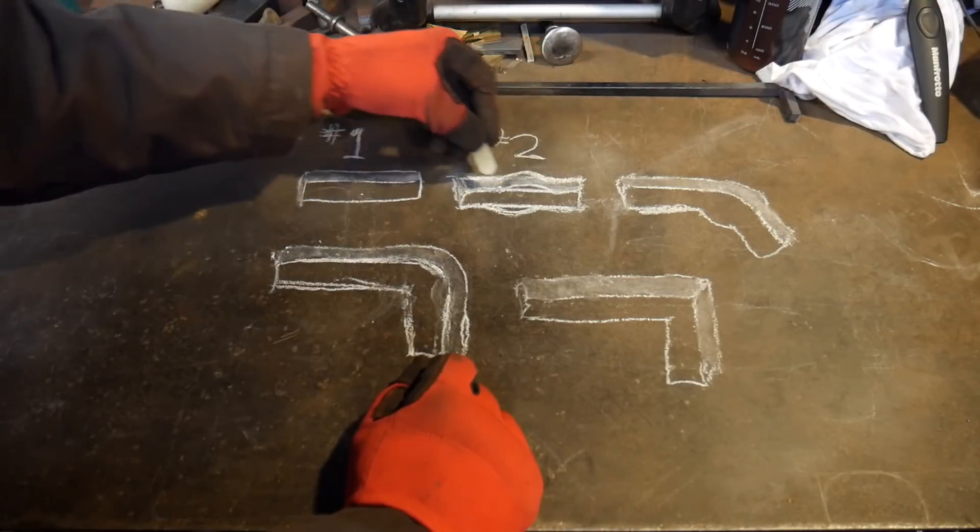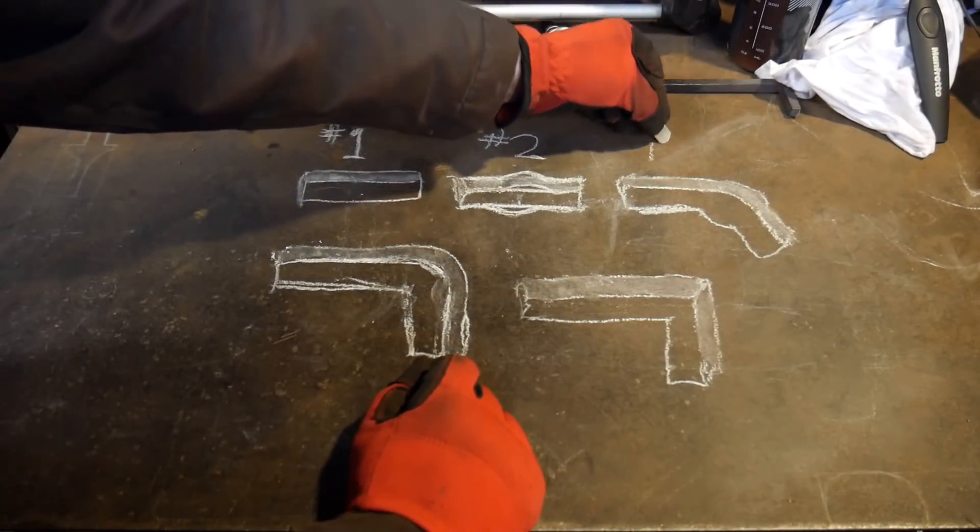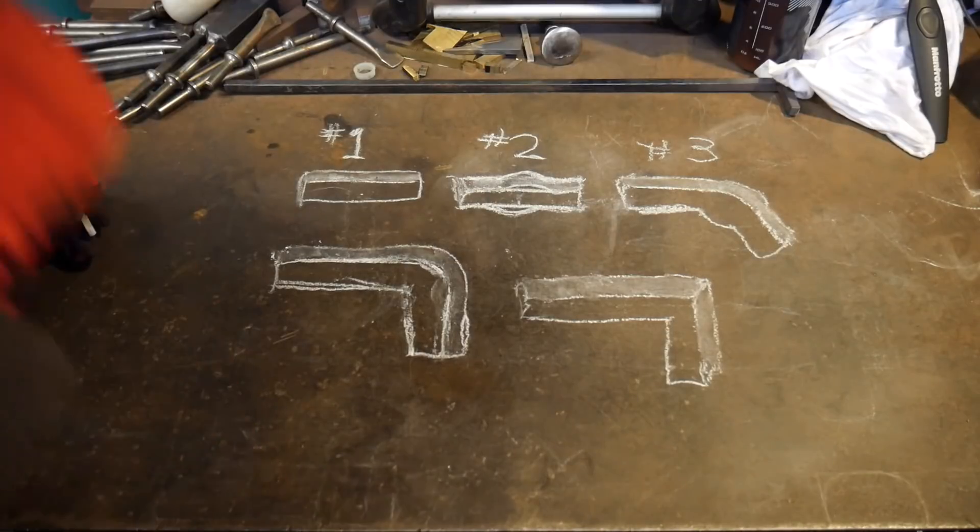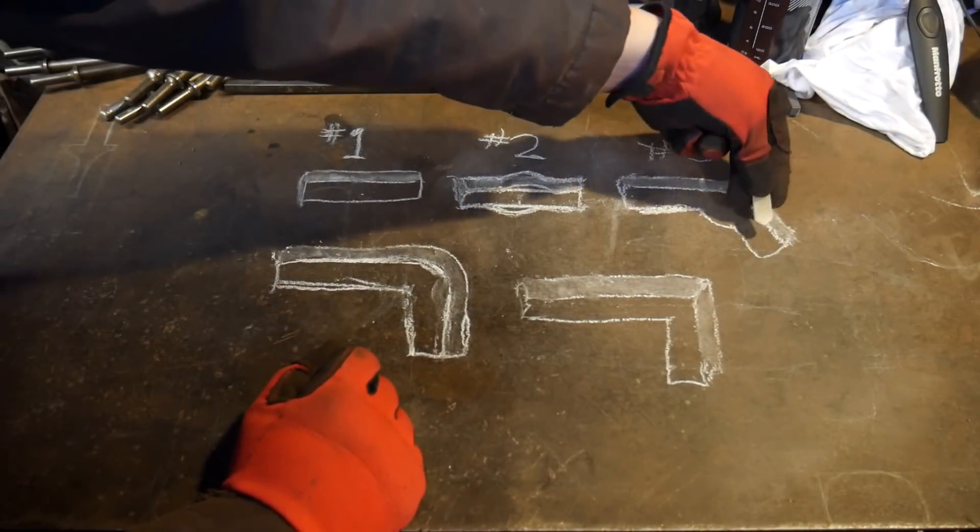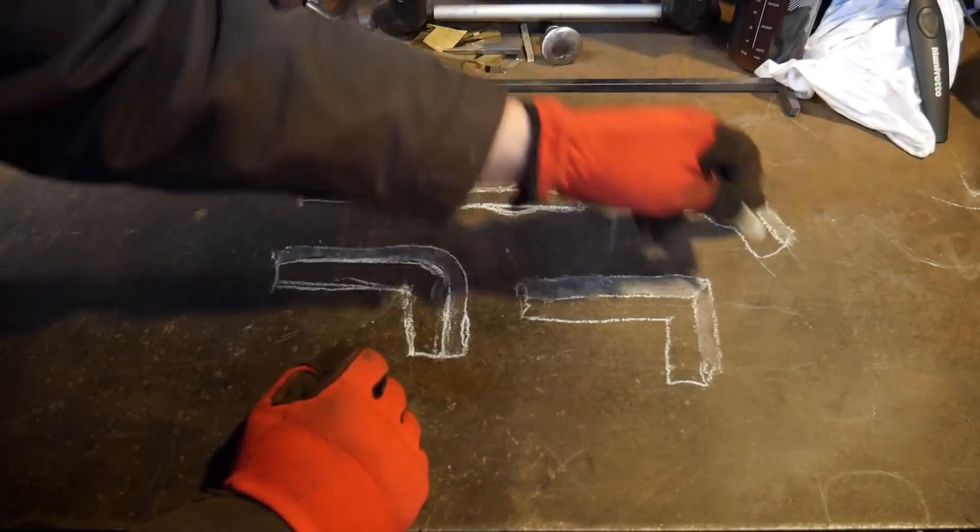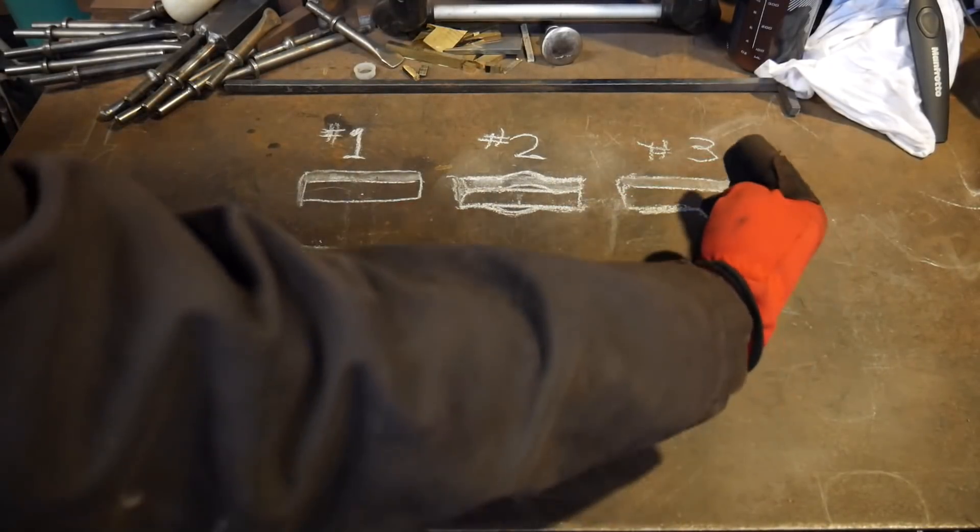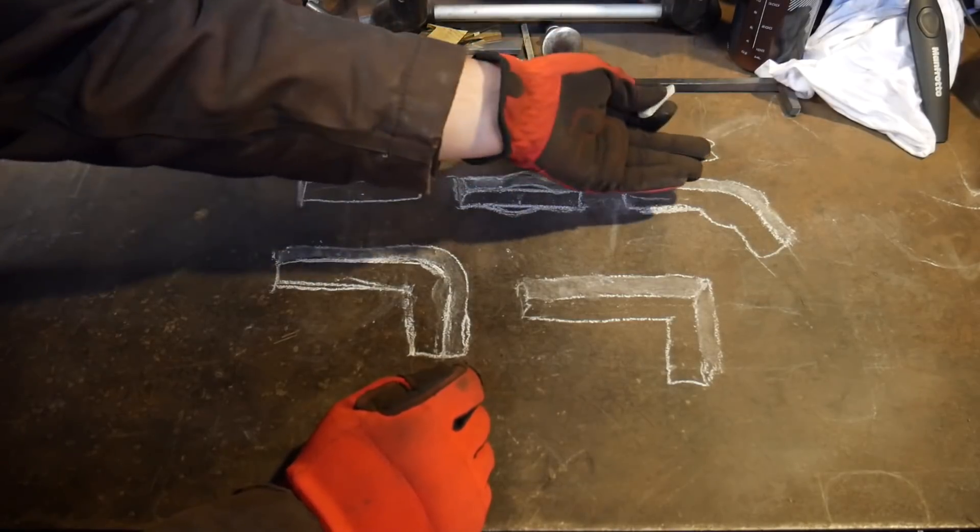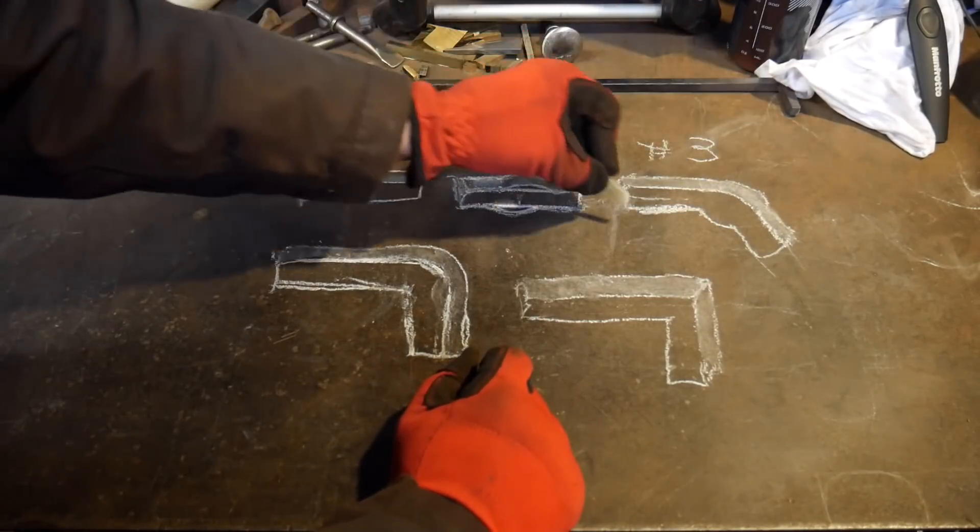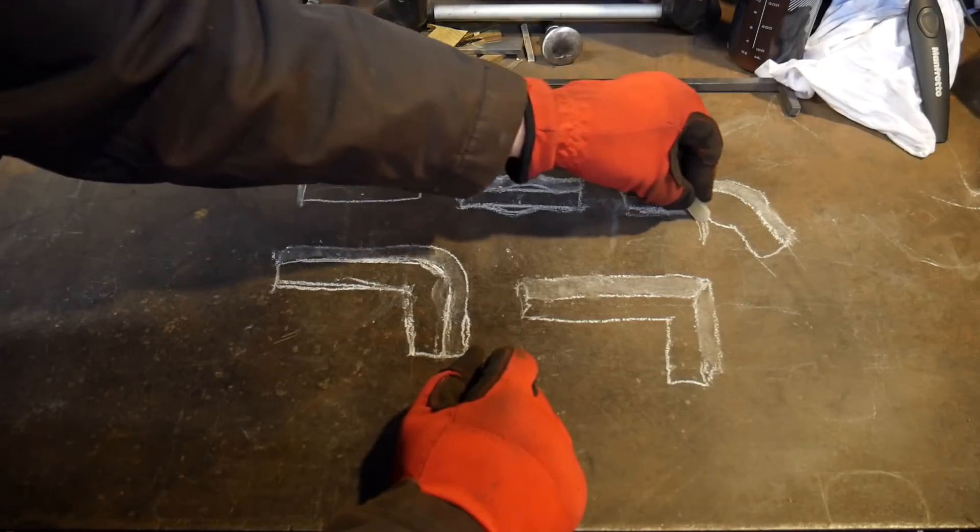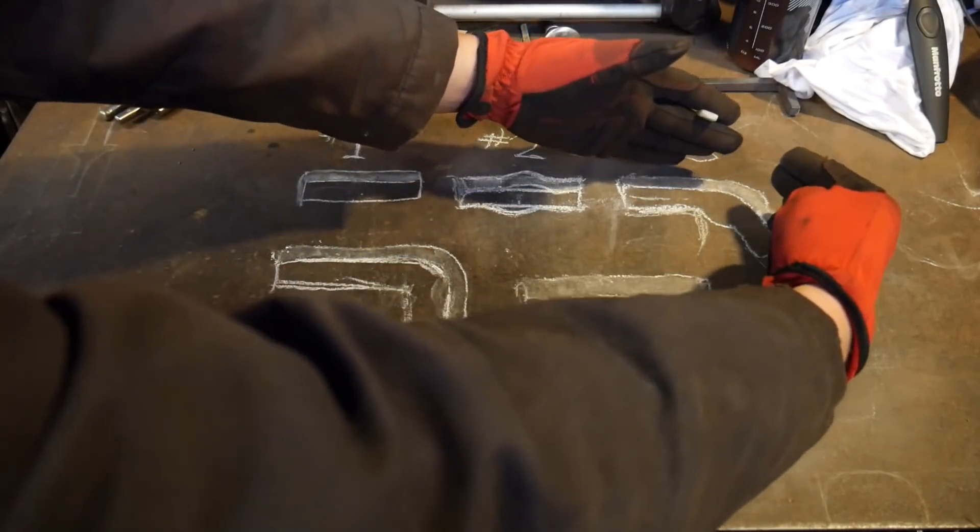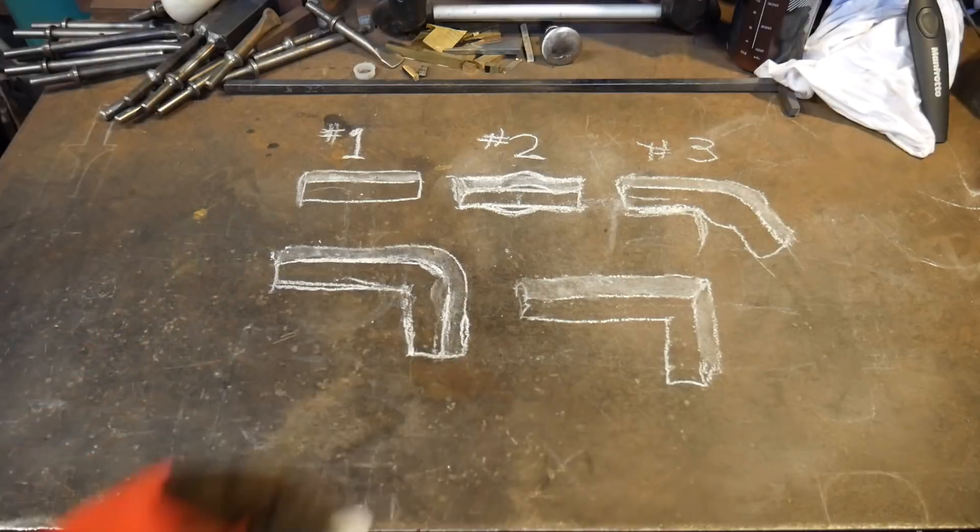Step three, after this short upset has been made, you need to do the initial bend. Now, the initial bend is just to start putting the material in the correct places where you want it to be. You know that this portion of the bar, however long it may be, is going to be one part leading up to the bend, and your original parent bar stock is going to be the other part leading up into that corner. And we need to start that over the edge of the anvil. So if you picture the edge of the anvil, it's somewhere about right in here when we start that bend. We just need to be able to get that mass, that outside corner mass, to start bending or arcing.